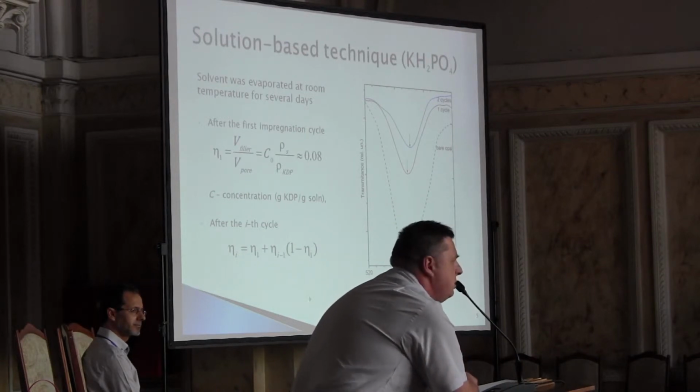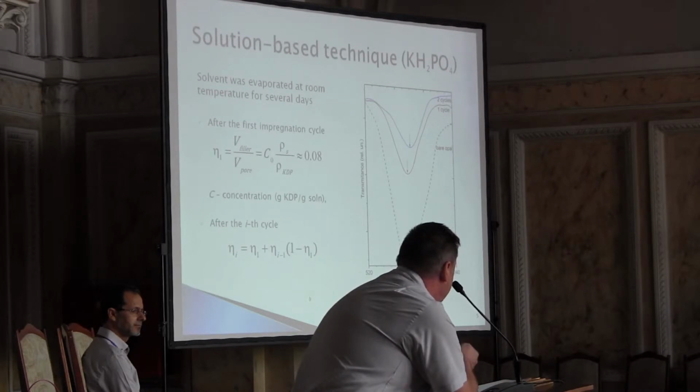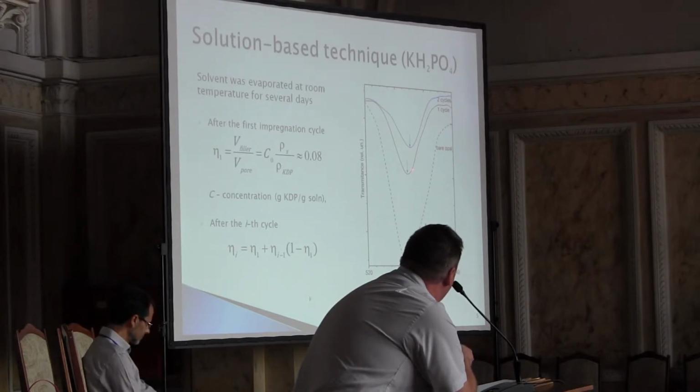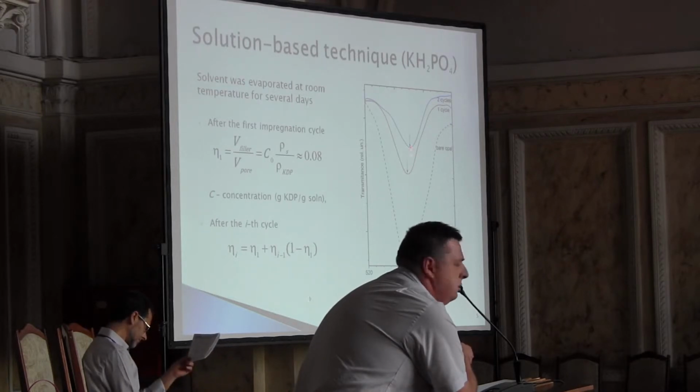After several cycles, the interference non-transmission minima in the transmission spectra of such structures are redshifted, and the filling degree is defined from this shift very well, and it correlates with the calculated one.